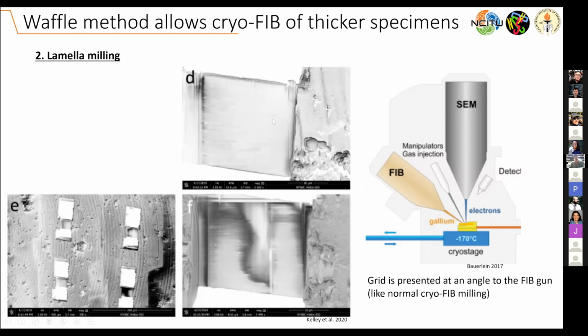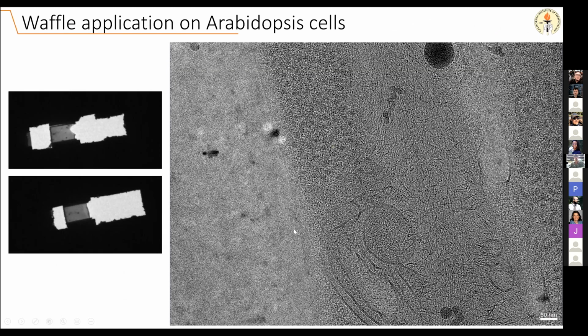And so by doing this, we can generate lamellae on thick vitrified samples. And so here are examples of two waffle lamellae that were done on plant cells. And this allows us to observe them by cryo-electron tomography afterwards. And so here you can see a snapshot. This is just a 2D projection where we can see the cell wall. You see all the fibers, all the cellulose fibers in the cell wall, the cytosol here, and here you have the vacuole.